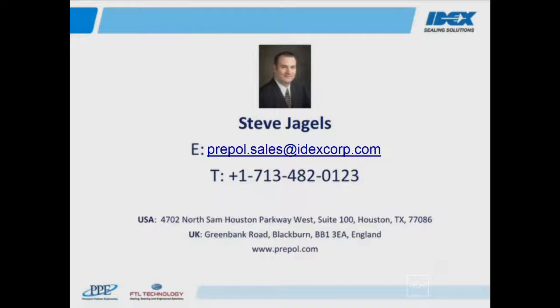Just a follow-up question to what we were discussing earlier. The RGD rating after aging in HPHT conditions, is that in a particular test fluid? The RGD testing, we've conducted a number of tests. The NORSOK M710, for instance, is just a gas test. So the standard gas percentage, the 90% methane and 10% CO2.